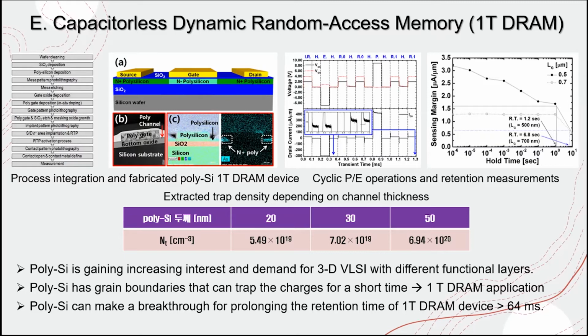Polysilicon can be introduced as a channel material into the one-transistor DRAM, and it has grain boundaries, crystal line structures, very minute structures under the gate in the channel. So it has the effect of trapping the carriers for a very short time, but relatively longer than the diffusion time of naturally disappearing carriers. The experimental results show that more than 1 second, reaching up to 6.8 seconds, were achieved for retention time. This was published in Electron Device Letters 2 years ago.